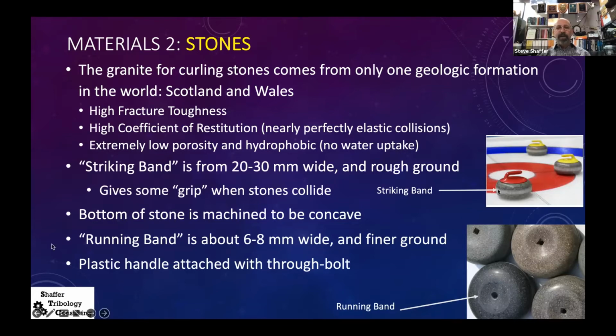And here we see the striking band, and it's an inch wide or so. It can be plus or minus that. And it's roughly ground, and that gives the stone some grip when they collide. It also cushions it a little bit. It turns out that if they're very polished, the collisions are too elastic, and the game changes in that case.